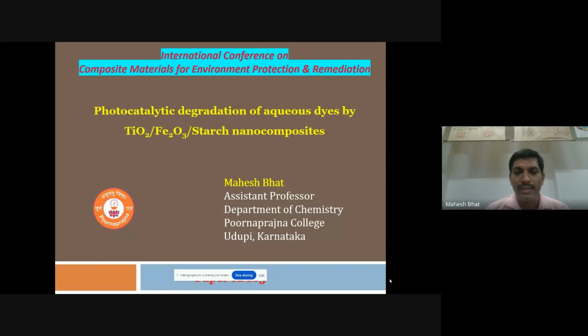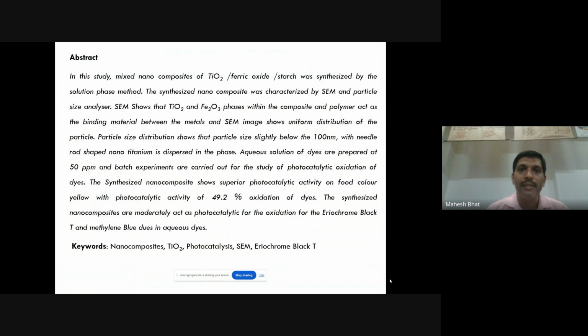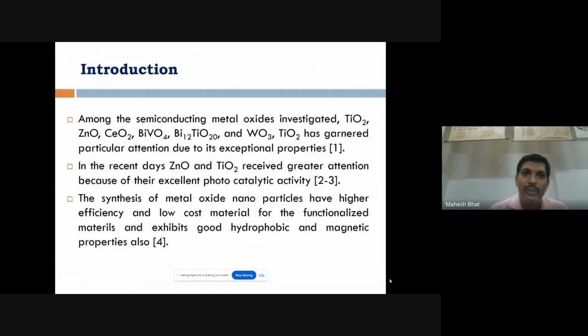Myself, Dr. Mahesh Bhat, Assistant Professor working in the Chemistry Department, Poorna Prajna College, Udupi, in Karnataka State. My research topic is photocatalytic degradation of aqueous dyes by titanium dioxide starch nanocomposites. In this study, we have synthesized the titanium-based nanocomposite material and analyzed it by SEM and DLS for particle size distribution, and utilized it for the photocatalytic oxidation of three dyes, namely food color yellow, eriochrome black T, and methylene blue dye solutions.